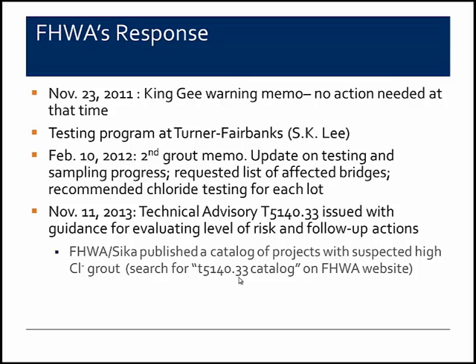The FHWA was also notified by TxDOT about that time, and so in late November of 2011, King Gee, an FHWA administrator, issued basically a warning memo to the 50 states, just alerting them that there were some issues with the grout and they needed to be diligent in their inspection and testing of the materials. They also started their own testing program running parallel with that Sika was going to perform, to be conducted at Turner-Fairbank Laboratory headed by S.K. Lee.